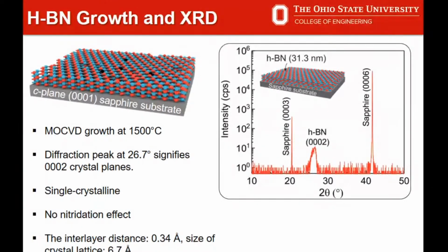As I mentioned, after performing some growth, you need to be very careful about the structural quality. The peaks seem quite broad, as you could see. But again, we got some single crystalline quality, which is good, I would say. And no nitridation effect is there, because we didn't find any kind of aluminum nitride peak in our XRD diagram.